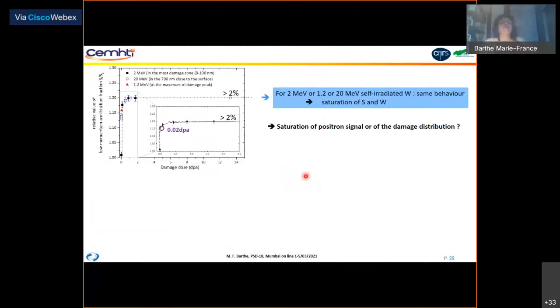If we now compare the data obtained at 2 MeV with other conditions, 1.2 MeV at 0.02 dPa and also 20 MeV at 1 dPa and also 13 dPa, we can see that there is no change of the S value as it has been observed for the 2 MeV tungsten. And so it seems that there is a saturation. And the question is, is it a saturation of positron signal or of the damage distribution?